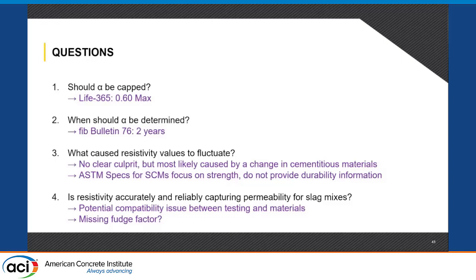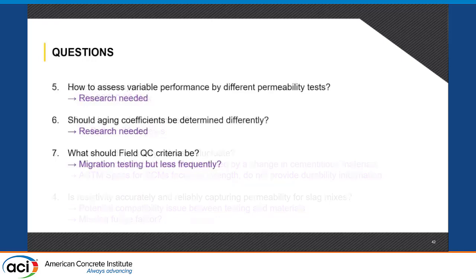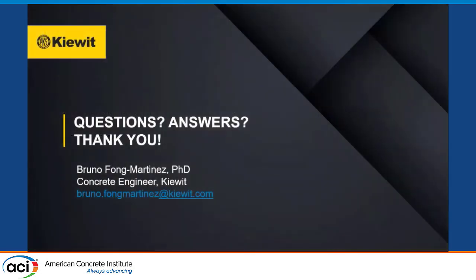The ASTM specs for cementitious materials don't focus on durability, they focus on strength. I think there's a compatibility issue between testing and materials, namely with electrical methods and the slag. Research is needed to address different performance, research is needed on how to really measure aging coefficient, and what the field QC criteria should be. I think maybe we should drop resistivity, focus on migration, and do it less frequently. References, and then questions. Happy to take questions, but also answers from you guys, because I don't know this. Experts in the field don't know it either, so we could use new ideas.